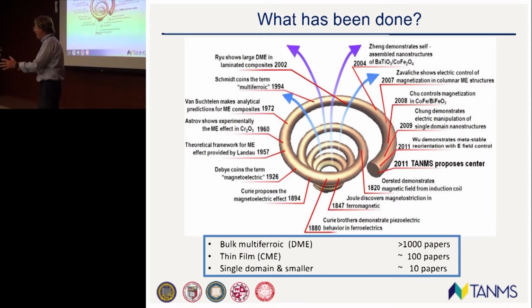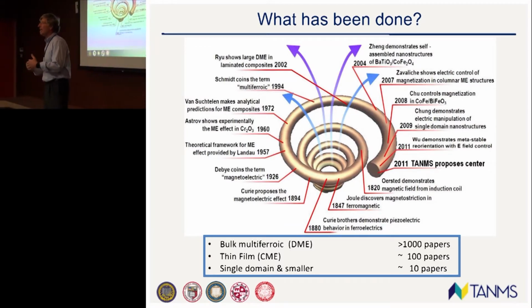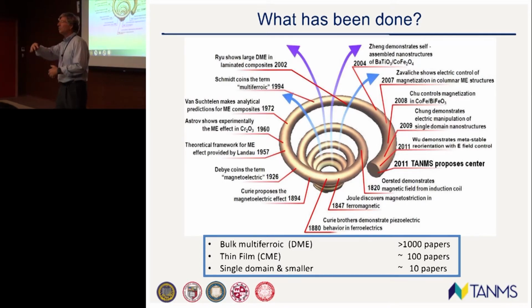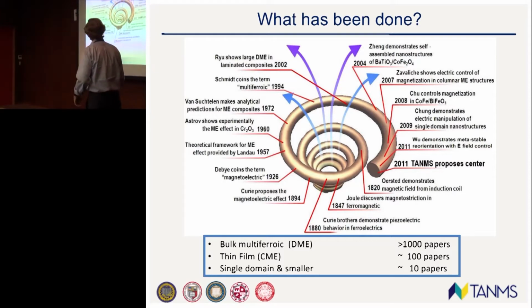And you may ask, well, why doesn't it work that well? Because there's domain walls in these soft ferromagnetic materials. So when you squeeze them, you're moving domain walls around. So instead of getting any magnetic change in the external surroundings, it just kills it. So you don't see any effective magnetic change in the surrounding area. And that's what we want when we control magnetism.